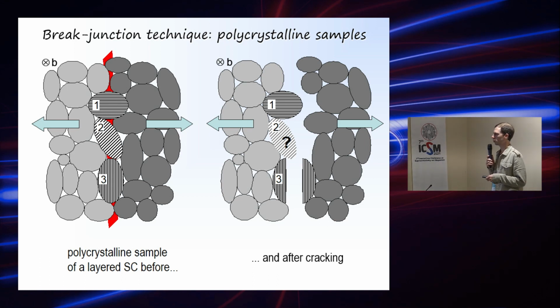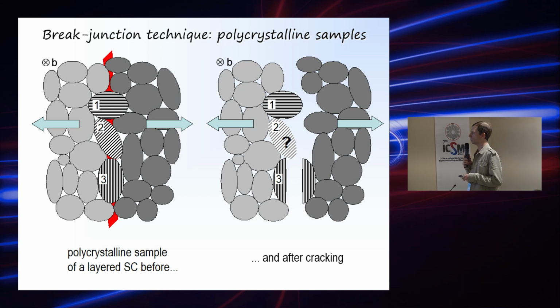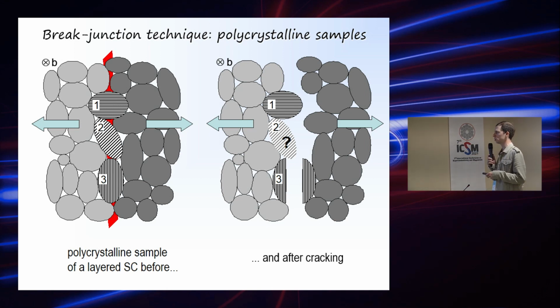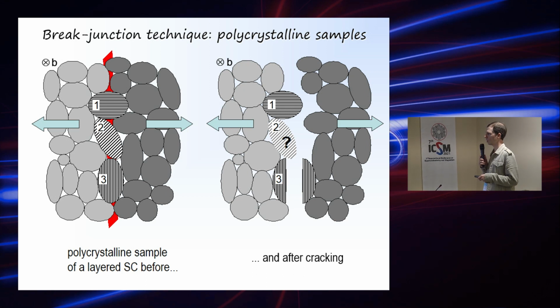It should be cracked or not. It simply depends on the combination of the angle, the ab planes angle orientation along the crack direction, and the ratio of the interlayer and intergrain strength, which is how strongly connected this grain is to its neighbors. Then it could be also broken or not.